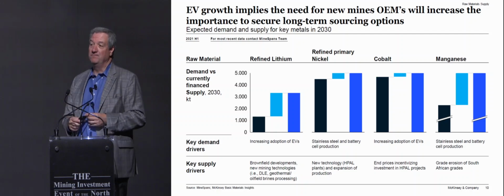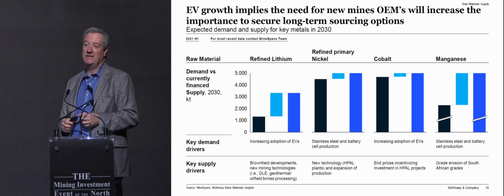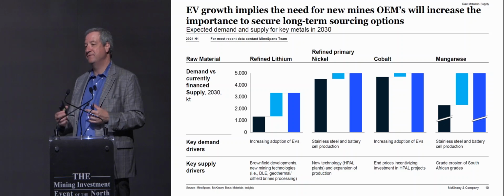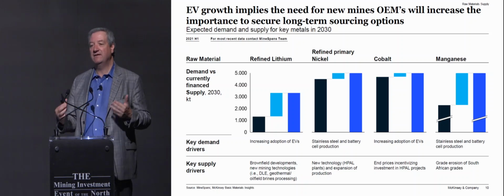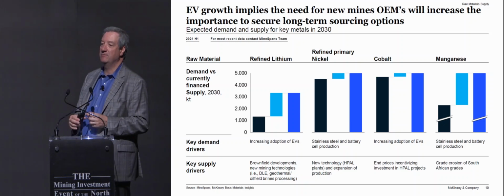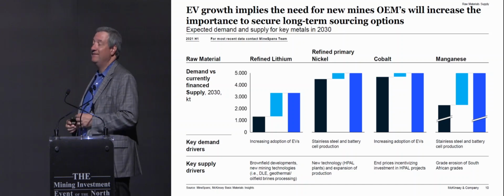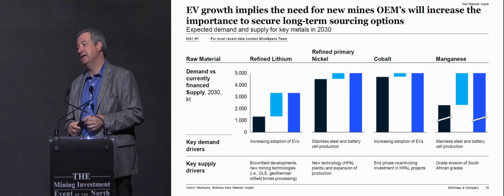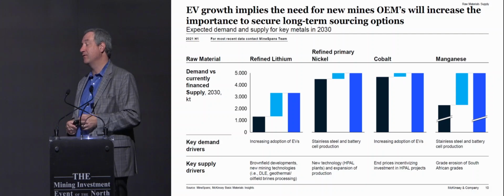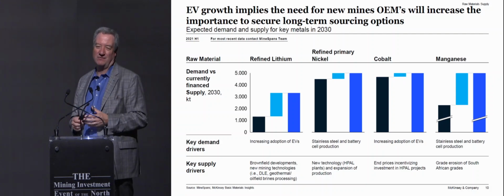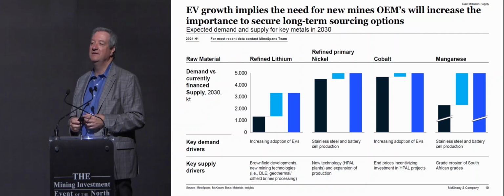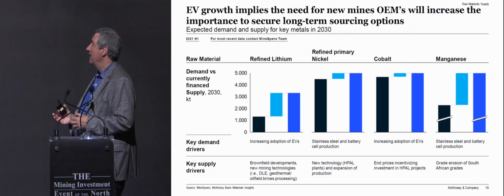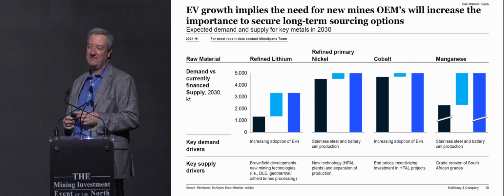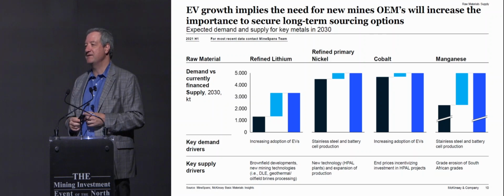Nickel is a problem, because only what we call class one nickel can be used for batteries. It cannot be a ferro nickel. It must be sort of an LME grade nickel, and even that needs to be refined a bit. And there's not much class one nickel out there, particularly if we want to see growth. As I said, around 300, 325,000 metric tons of nickel was used last year, of about 1.7, 1.8 million metric tons of class one nickel.